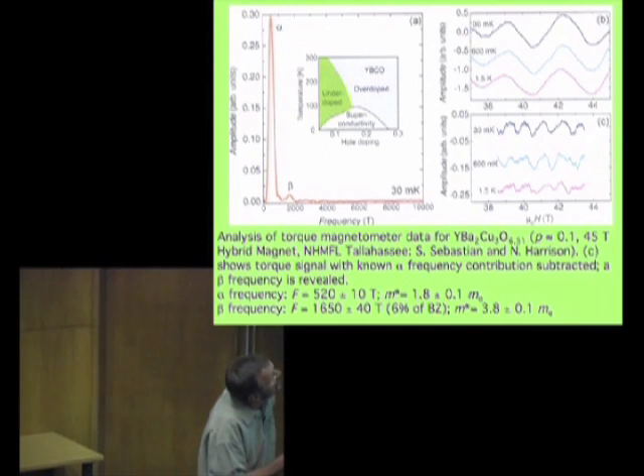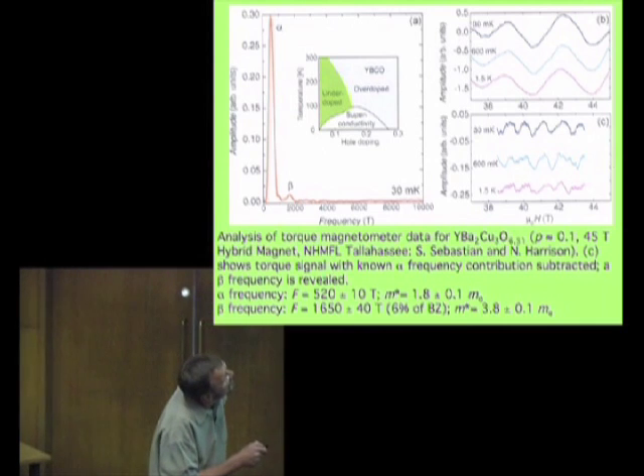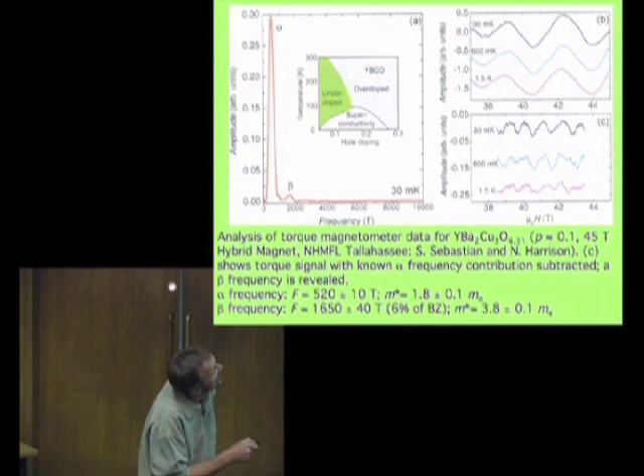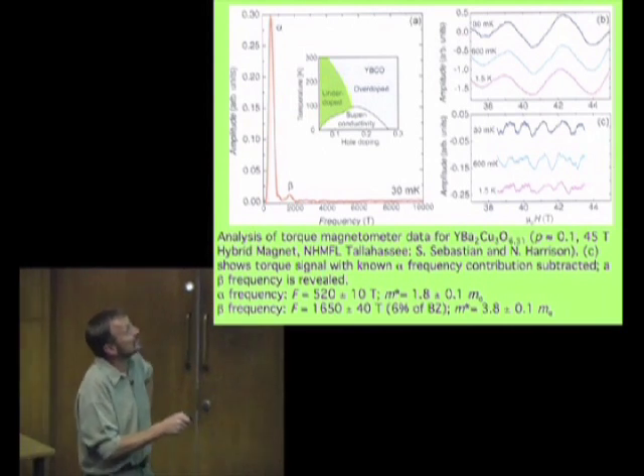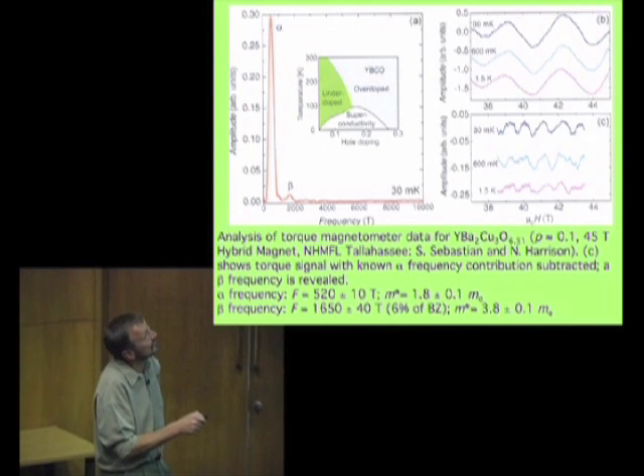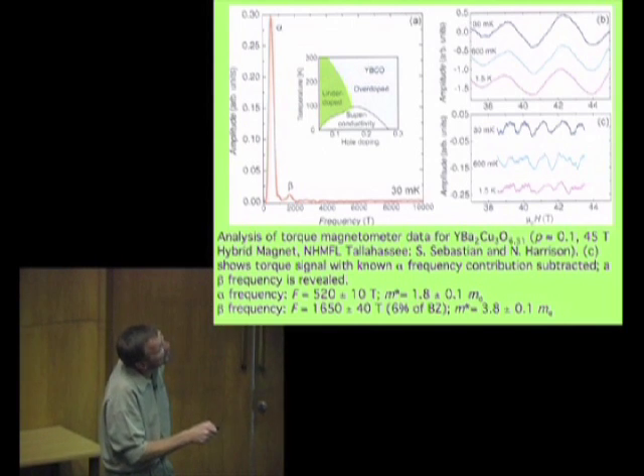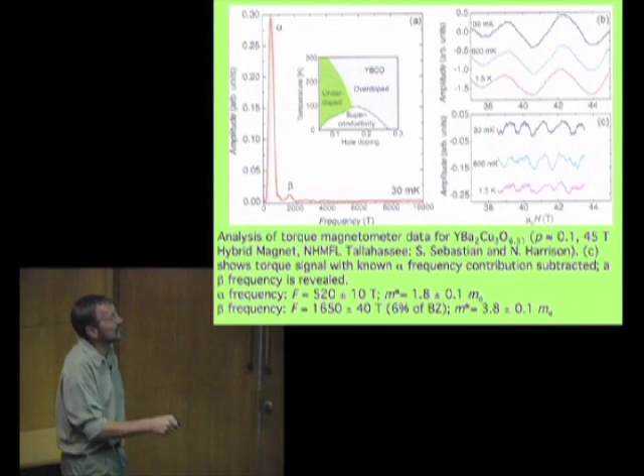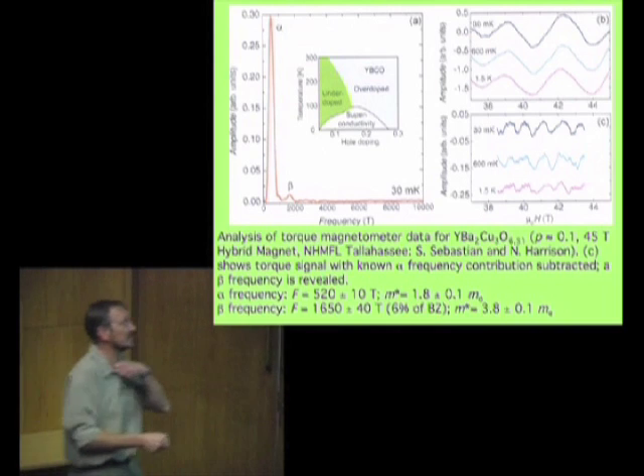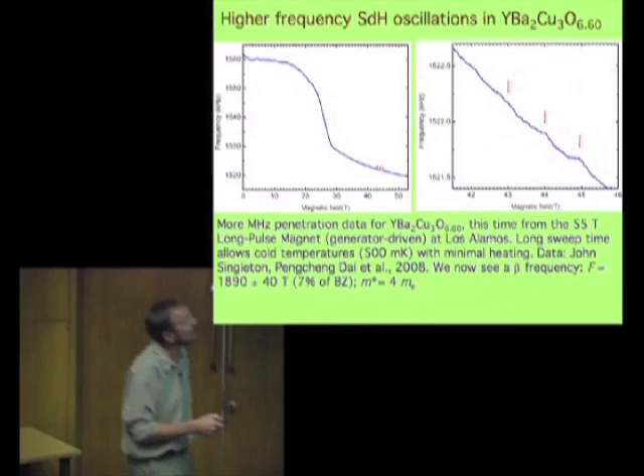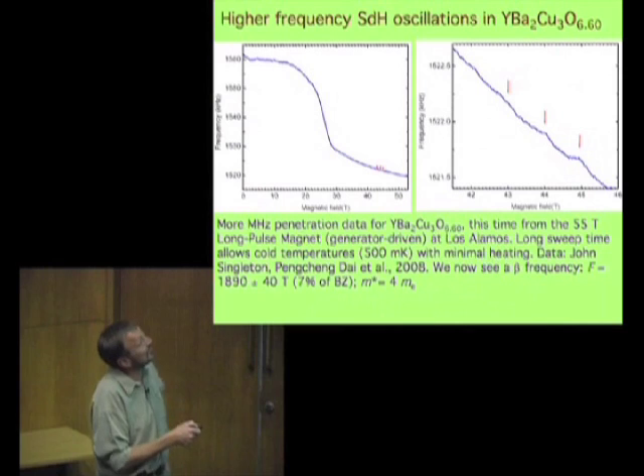Now, in the raw data, even with a very careful background subtraction, it's very difficult to see this frequency. There's one of the oscillations here. But if you take out the lower frequency, the 500 Tesla one, which are these prominent oscillations, you get left with a further series of oscillations which have a frequency of about 1,650 Tesla. These are seen in some of the other dopings as well.